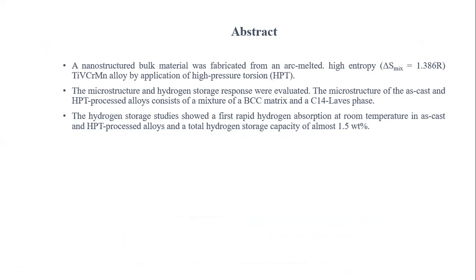A nanostructured bulk material was fabricated from an arc melted high entropy titanium, vanadium, chromium, manganese alloy by application of high pressure torsion. The microstructure and hydrogen storage response were evaluated. The microstructure of as-cast and HPT processed alloys consists of a mixture of BCC matrix and C14 Laves phase.